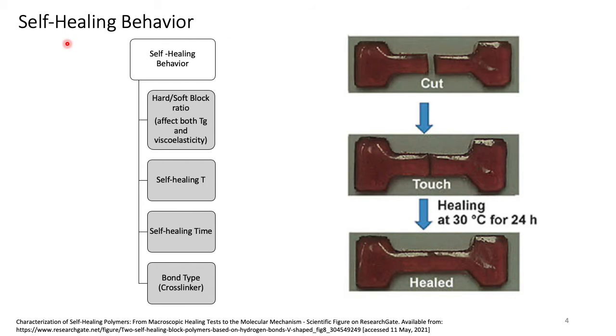In order for us to understand the self-healing behavior of block polymers, we need to know what parameters affect the self-healing ability of these materials, going from the cut state to the healed state. The first one is the hard to soft block ratio, which affects the glass transition temperature and also the viscoelastic behavior of the material. Also the self-healing temperature, which is the ambient temperature that we are testing the material in. The self-healing time, how long we wait for the material to self-heal. Also the bond type, which can be affected by the type of cross-linker.